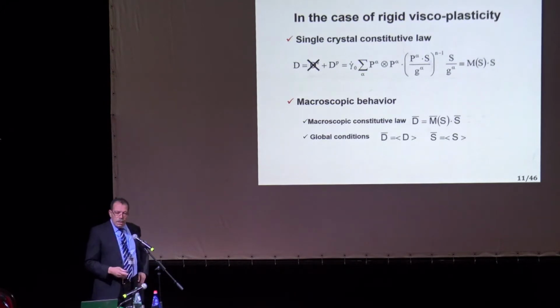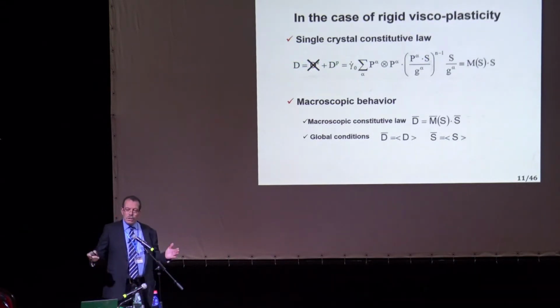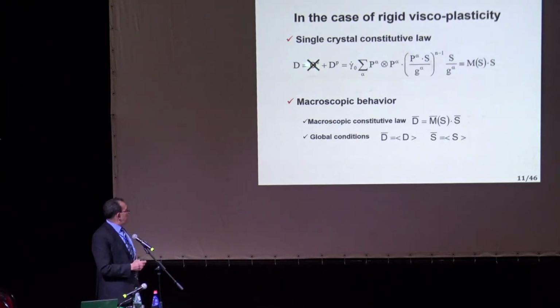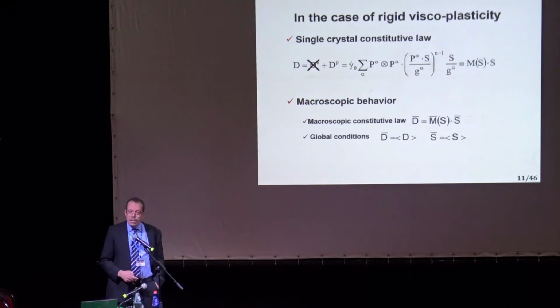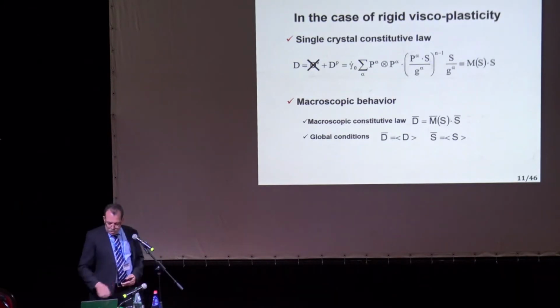Now, the single crystal has elastic and plastic parts. So D, the strain rate, is elastic plus plastic. But since I'm dealing with large plastic deformation, we neglect elasticity. It does not affect at all the microstructure evolution. So we neglect that. D is equal to D^P. And if I use the relationship before, then I end up with a relationship like this. So D is M S. M is the compliance tensor, and S is the stress.